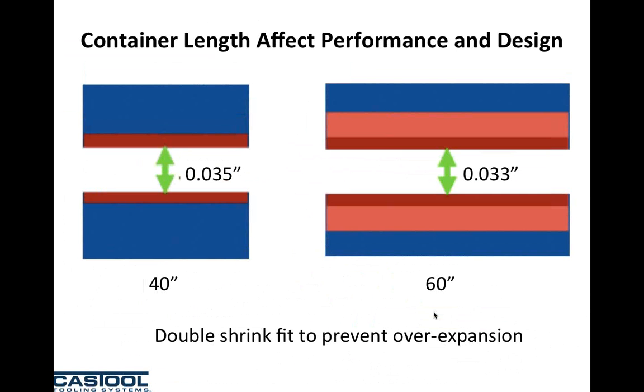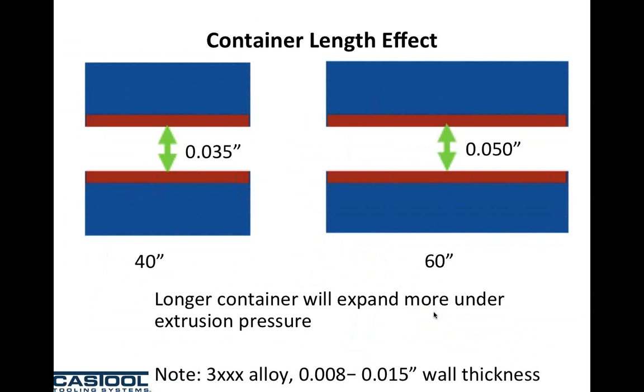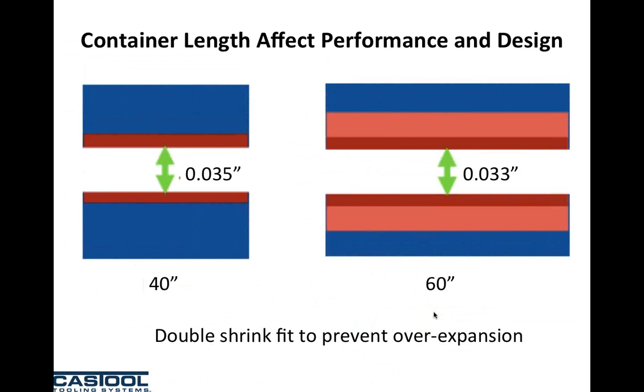If we then make that 60-inch container three-piece with the proper shrink fit, we can decrease the expansion of the bore to 33 thou versus 50 thou. Basically, bring it back into a stable condition where we're not going to be affected by aluminum blowby in the liner. This seems to be something that a lot of people are not paying much attention to in the marketplace. And it's not the dummy block's fault. If you have a dummy block with a 60-inch container and your container is two pieces, you're going to have a problem.